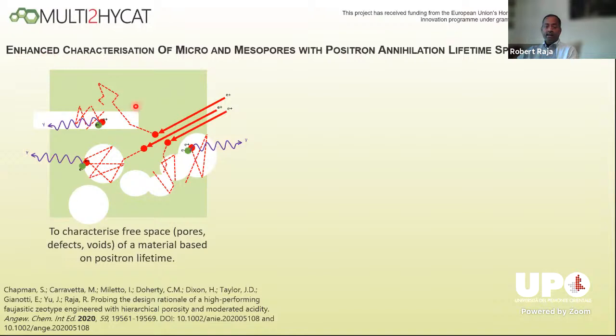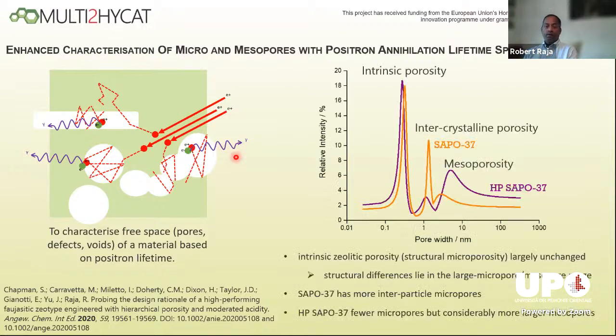The idea then is to look at the free spaces, pores, defects and voids in the material, and then you can follow the lifetime, the tau values, of this positron decay, and you can start to map out what the pore architecture might look like. So with this SAPO-37 catalyst, we fired these positrons at it, and we looked at the decay of these positrons within this particular structure. And one can see here the similarities.